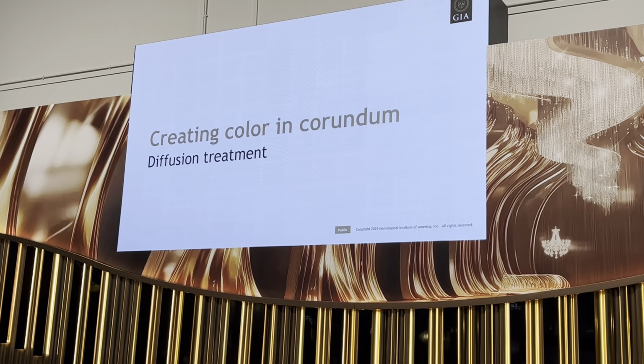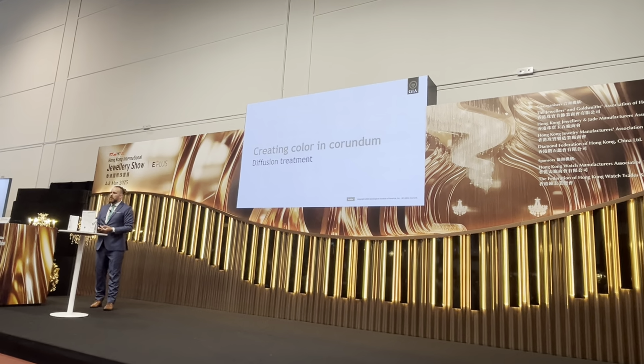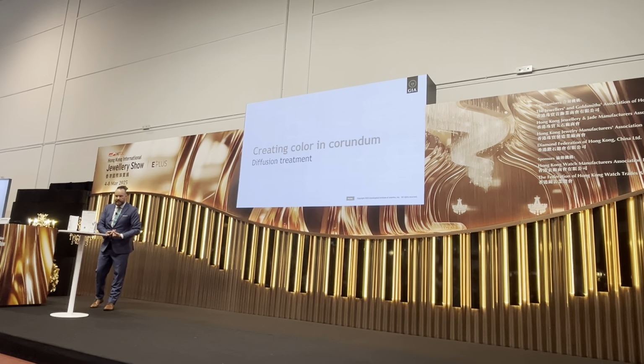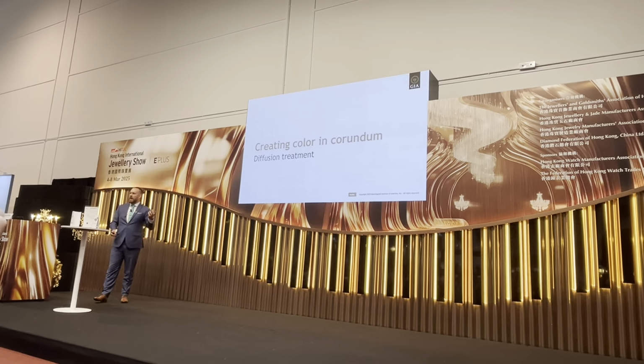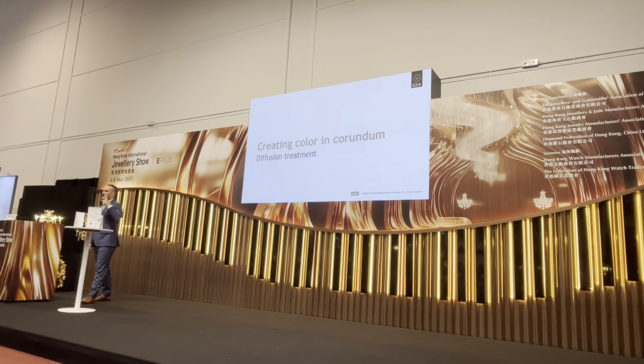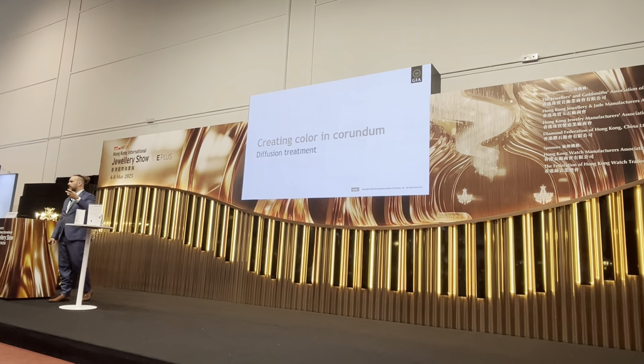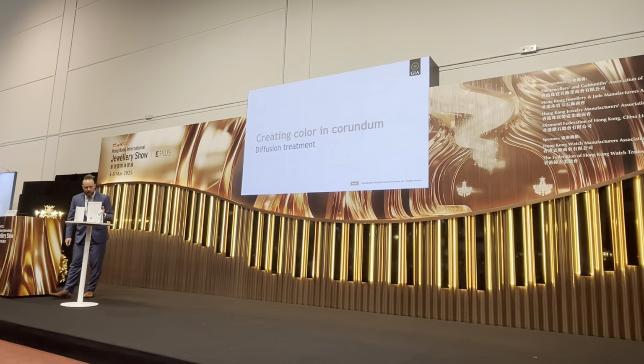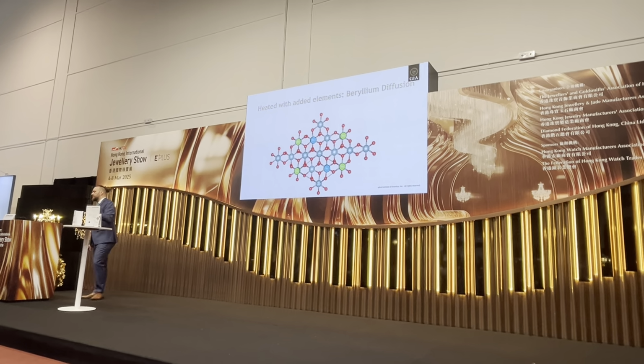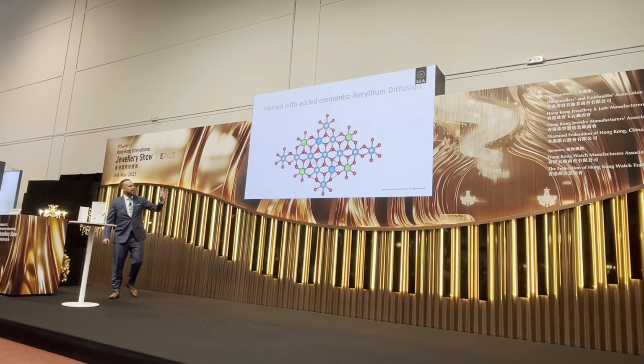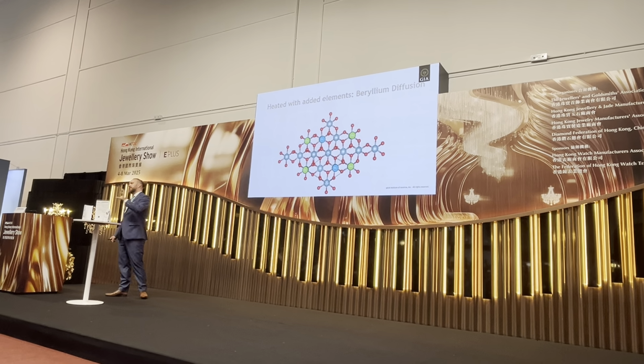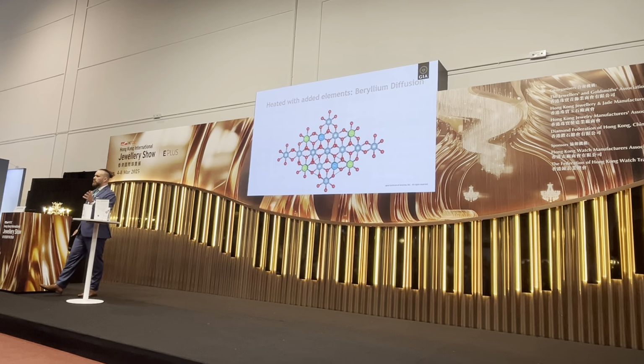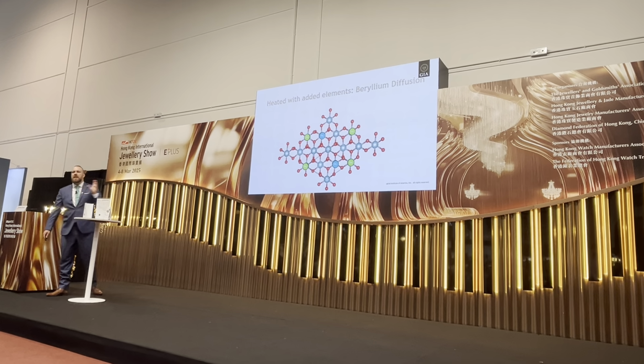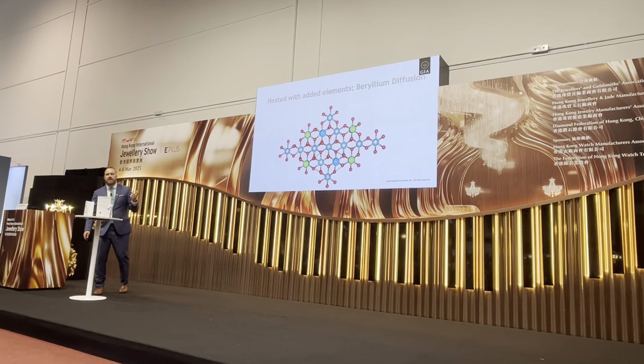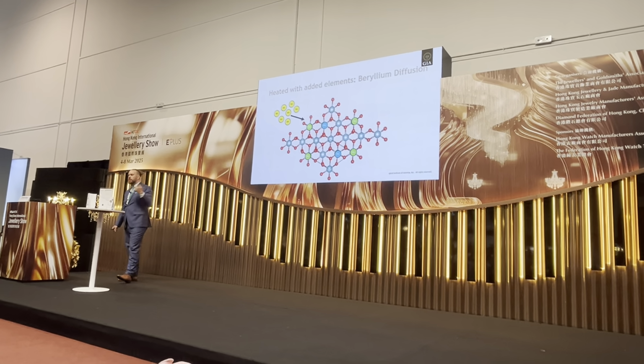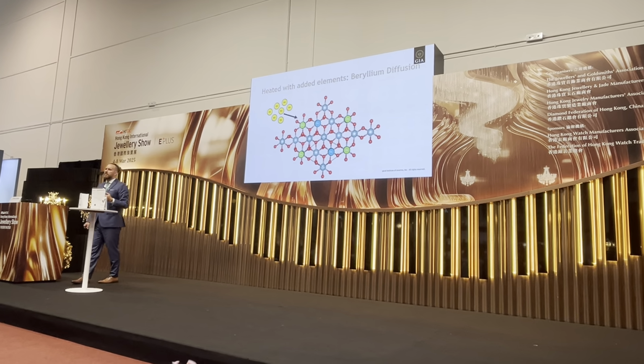Now, another thing that we can do with corundum is create extra color in it. We can heat it with extra elements added to it, and these extra elements will create extra color in our corundum. I'm going to go through this very fast because we know that in blue sapphire, for example, most of the color is created by iron and titanium. In ruby, it is because of chromium. But with iron and titanium, we can play around with it, and we can actually stuff other elements in there that will interact with it.